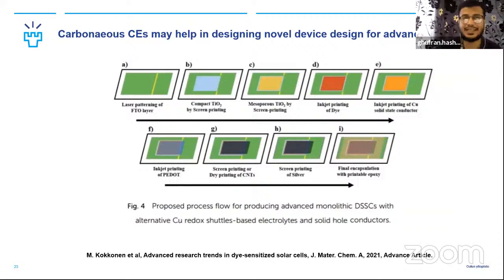So we can really design based upon the printed carbonaceous counter electrode material, instead of the two electrode geometry of a solid state device design. You can produce these cells on a single substrate by first laser patterning the glass electrode to obtain the contacts for both electron and hole transportation. And then you can grow on one side the electron transporting layer. Now we know how to do it, either by screen printing a compact layer, or by TiCl4 treatment, or by spray pyrolysis.